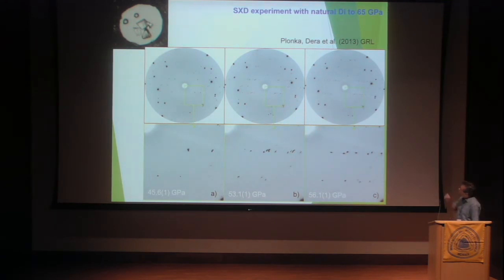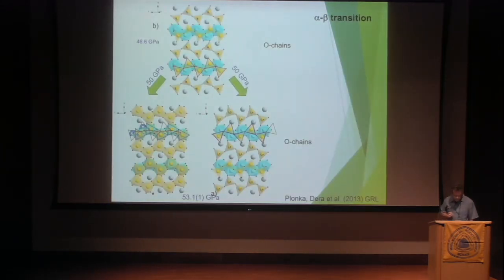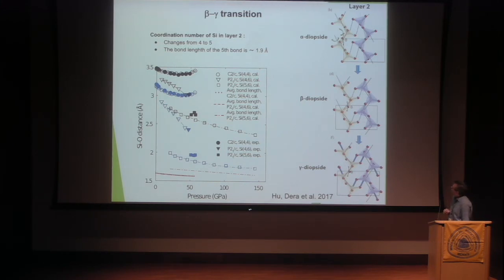You can see that there's a point at which there's a very clear rearrangement of the geometry of diffraction peaks. When we solved the structure, we discovered that half of the silicon transforms from the 4-coordinated state into a 6-coordinated state with an average coordination number of 5, but no 5-coordinated silicon present. But then if we squeeze the sample a little bit harder at another 5 GPa higher, we observed formation of 5-coordinated state, again, just by rotation of the tetrahedral chains.